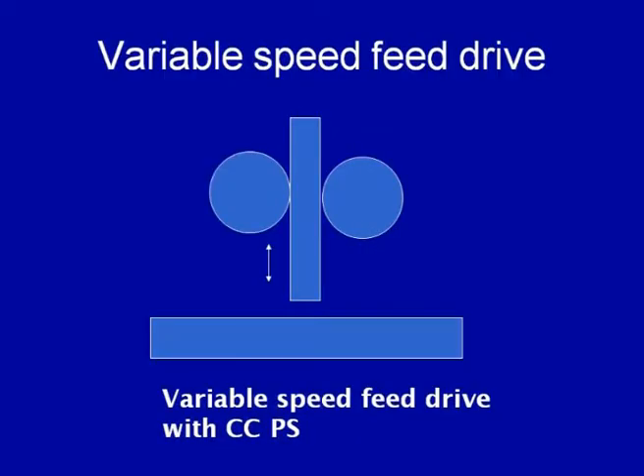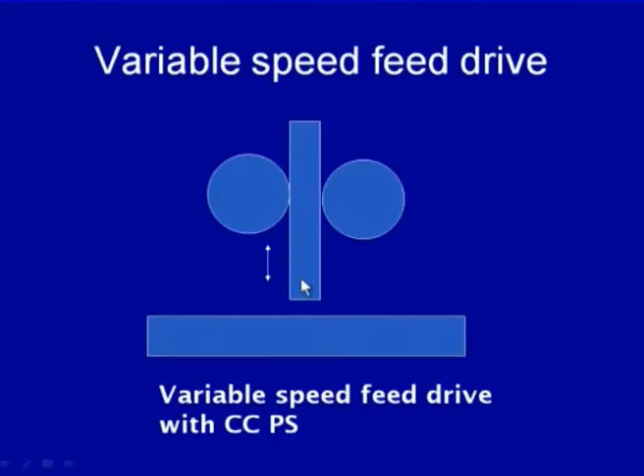Another approach is the variable speed feed drive system. Under these conditions, the constant voltage type of power source is not used, but this kind of feed drive system is used when the electrode diameter is large enough and the electrical resistivity is also low. So, the variation in current does not affect the melting rate as significantly as in the case of a small diameter and high resistivity materials, and in this case the melting rate is primarily governed by the first factor, that is the A I term of the melting rate equation, instead of the second factor where I square R was dominating in the earlier case. So, under these conditions where change in welding current does not significantly affect the melting rate, the arc length is maintained with the help of variable speed feed drive systems.